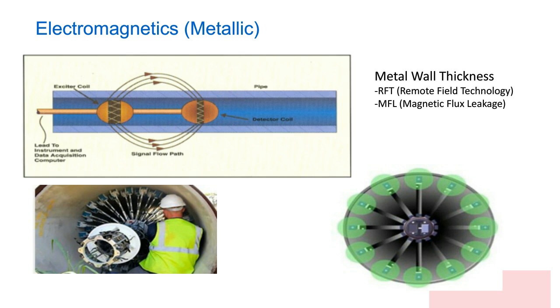So without getting into the in-depth of it, that is essentially what you're looking for, changes in magnetic flux. The key to this type of technology for metal wall thickness or localized pitting is you need to have these sensors, and you can see in this particular diagram, the sensors need to be in very close proximity to the surface wall. If it's too far away, it becomes very difficult to measure the magnetic flux. And I want to have as many sensors as possible to measure the complete circumference of the wall on the inside. And last, you can see the tool down in the lower left, you can see all the sensors, very large piece of equipment that you need to push through the pipe or pull through the pipe.